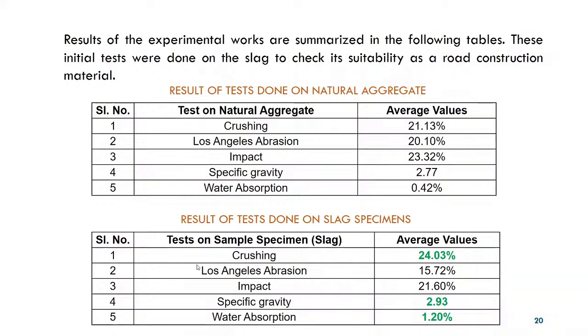For the slag specimen, the crushing value was more than the normal aggregate. The specific gravity also was within the range, only 2.93, water absorption also very fine, and the abrasion and the impact values of the slag specimen were much better than those of the natural aggregate.